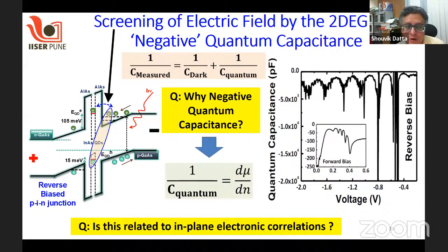contribution of the 2DEG in these measurements of capacitance, and we actually tried to see if the measured photocapacitance can be split into two parts. One is the dark and another is the quantum capacitance as a result of the screening effect of the electric field by the two-dimensional electron gas that is there in the top. And with that, when we deconvolute our capacitance in terms of quantum capacitance, we also see that the quantum capacitance is negative.